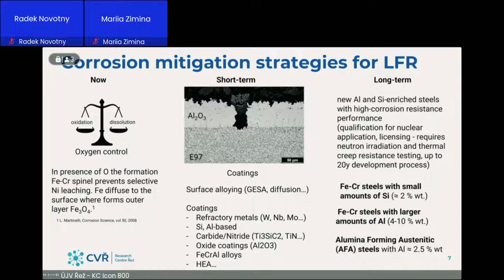And the ultimate solution is to have a material that is resistant. You can reach it by addition of silicon to ferritic martensitic steels. That is the Russian way. It can be successful, but it has some impact on mechanical properties. The European way is to add alumina or aluminum to austenitic steel to get this material. The problem is that qualification of this material is very long, and it requires some creep testing, and that's why I think that some demonstrator will be based on an oxygen strategy with some coatings.